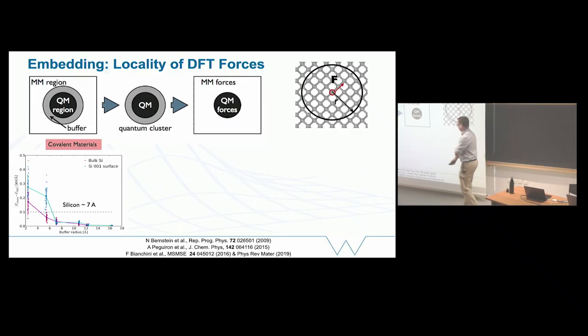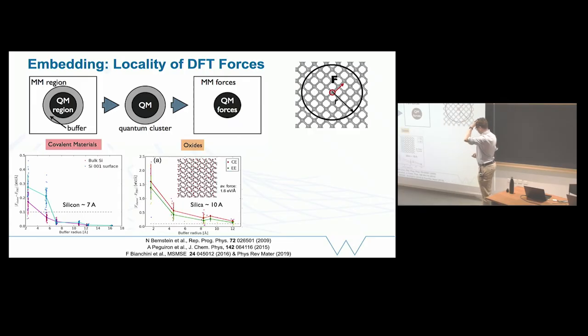And in covalent materials, this works well. So you need 7 or 8 angstrom, and you get within a few % accuracy with your forces. In oxides, it's terrible, and really it doesn't work at all. Even if you try more advanced approaches, like embedding the DFT calculation itself in the electrostatic field that arises from charges and dipoles centered on atoms outside, it still doesn't help too much. So the red is cluster embedding, and the green is with the electrostatic embedding, but still you have to go to very long distances.